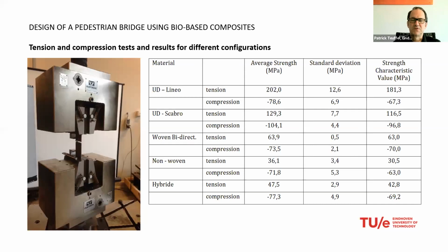So UD stands for unidirectional fibers. So all the fibers are orientated in one direction. Then we have woven bidirectional fibers. So as the name indicates, the fibers are orientated in two directions, and also non-woven and hybrid materials. And you can see, especially for the UD materials, the strength is actually quite high, so up to 200 megapascal, which is comparable to aluminium and only a little bit less compared to traditional steel. So I think that's very promising from a structural engineering point of view.